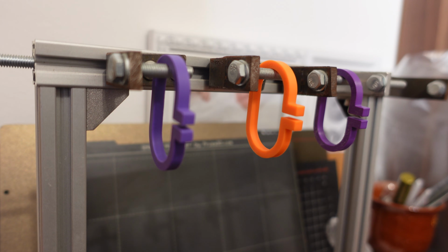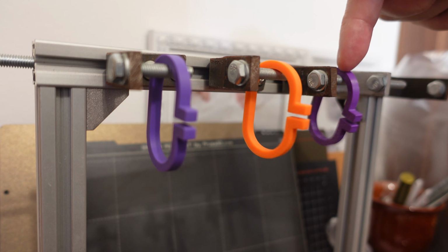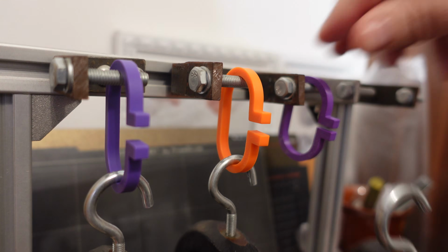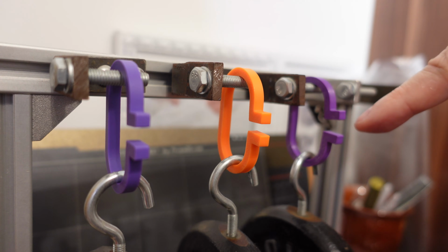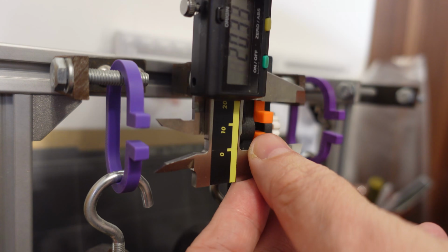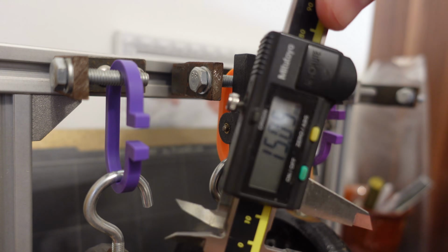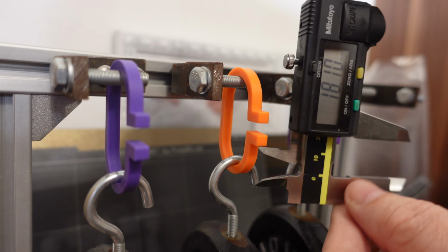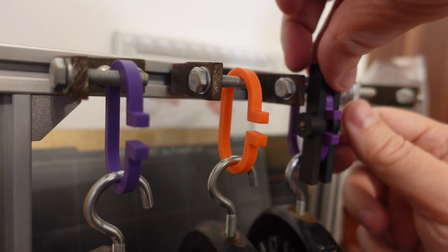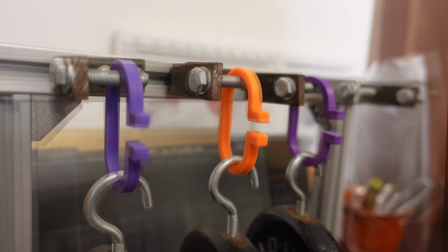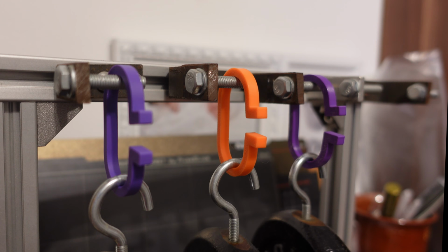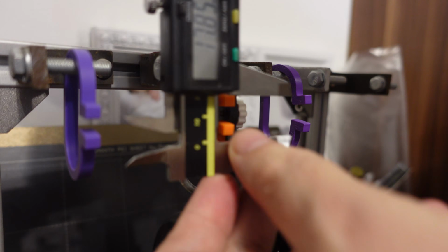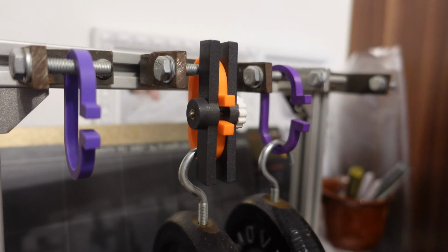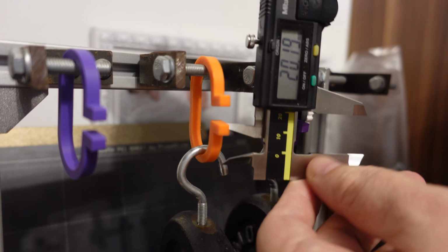Creep test, the deformation under constant load, PLA and PETG. Wow, more deformation on PETG. 15.05, 18.10. Day 5, last day of measuring, 17.85, 20.19.